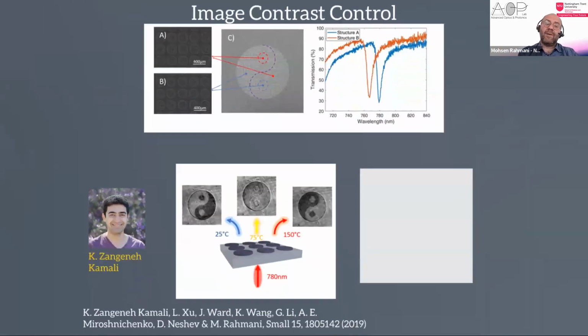So we used it a couple of years ago, by hard effort of my PhD student at ANU in Australia, Khosrow. We made a very nice yin-yang image composed of two different metasurfaces. Here, as you see, they are very similar, but slightly different in terms of dimension. That's why the wavelengths and the resonances are slightly different. So by looking at one wavelength and hitting the whole structure, you can generate an image, and you can control the contrast of the image only by controlling the temperature here.